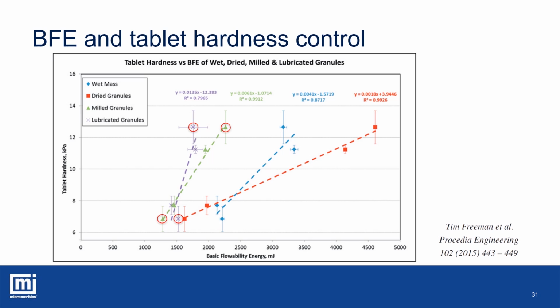I've moved the highlights to show which comparison I'm making now. The difference here is the presence of mag stearate and the blending process that introduced it. I think you could probably suggest that the blend time could have been extended and the shear rate increased to lower the errors in the BFE post-blending.